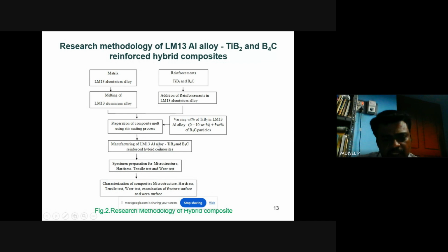Then the hybrid composite is analyzed for microstructure, hardness, tensile test, and wear test. These specimens were prepared to the standards, and with the standard specimens we have undergone the microstructure, hardness, and other tests also. Then after that, we characterized the composites' microstructure, hardness, tensile and wear properties, and the examination of fracture surfaces and worn surfaces.